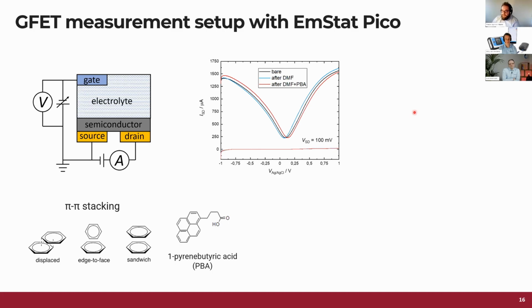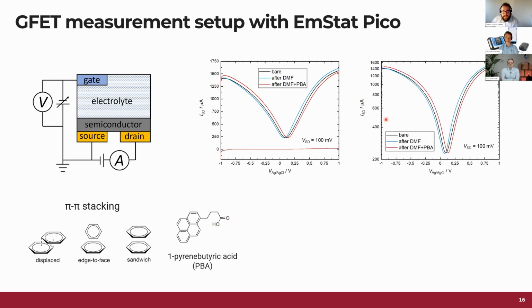This is most likely due to the desorption of leftovers of PMMA. And then afterwards, we immerse the whole device into DMF with pyrenes, and we can see some right shift in here. So from blue to red, there is a shift of surface potential due to the adsorption of pyrenes on the surface. This is a transfer curve of the graphene FET in a linear scale of current. This here is in the logarithmic scale. So we can clearly see that our on-off ratio is from about 1.4 thousand microamps to like 300 microamps.